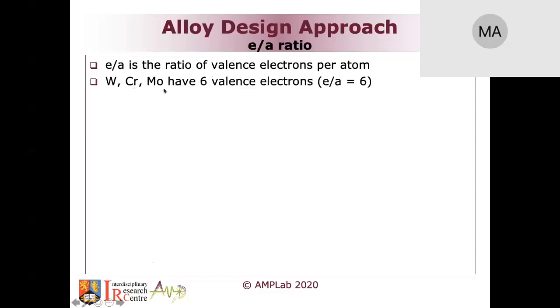Now, this is where we tried a little bit of the clever bit, and this is the part that made a significant difference. There is a theory for alloy design which relies on a concept called the E/A ratio, the valence electron per atom ratio theory. Essentially, the E/A is the ratio of valence electrons per atom. Elements like tungsten, chromium, and moly have a valence of 6, so the E/A is 6, whereas vanadium, tantalum, and niobium have a valence of 5.